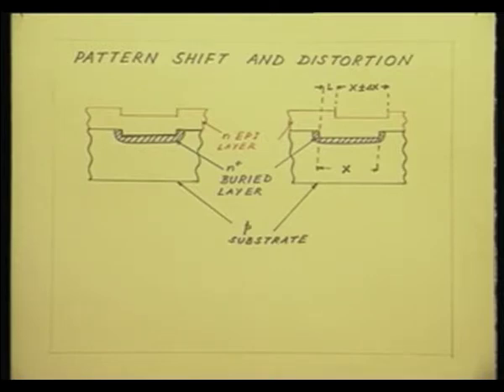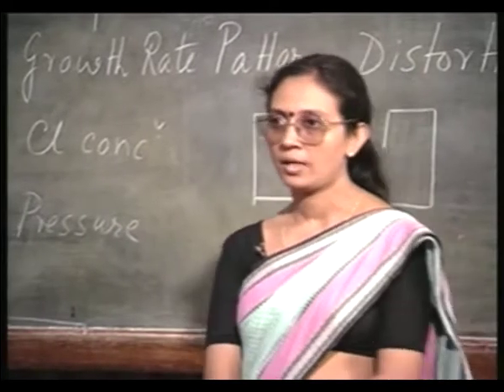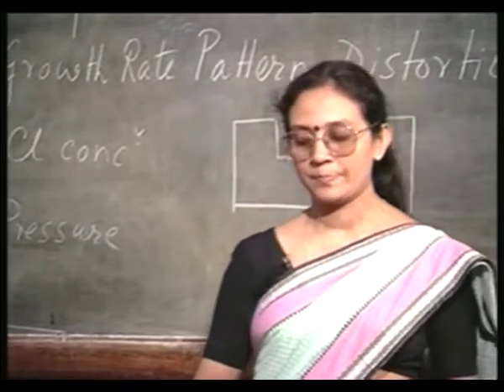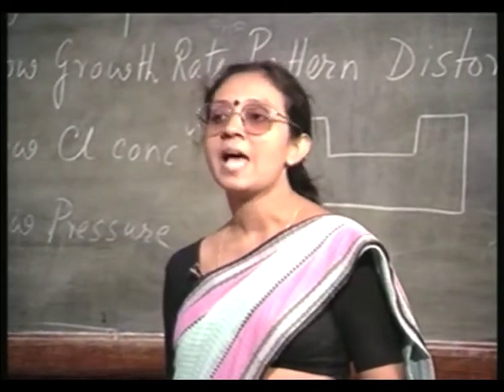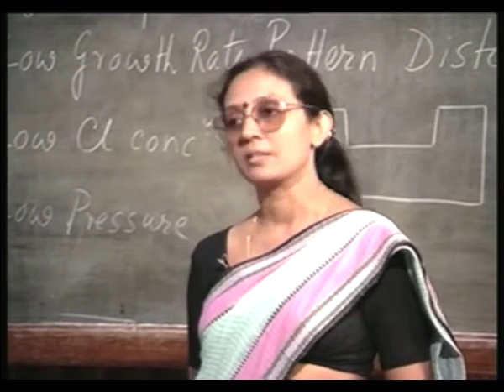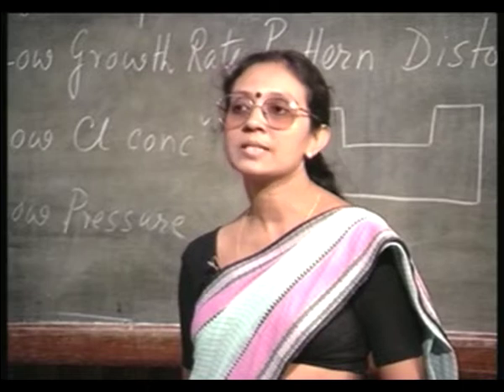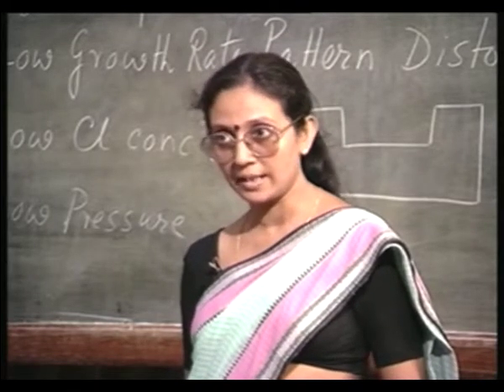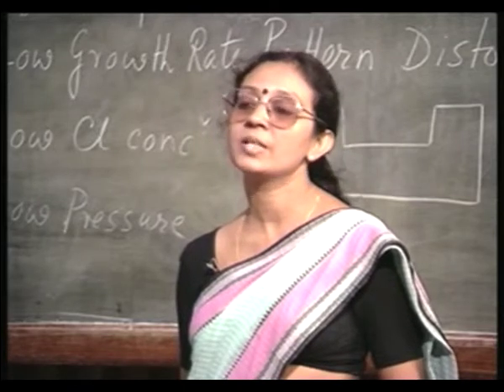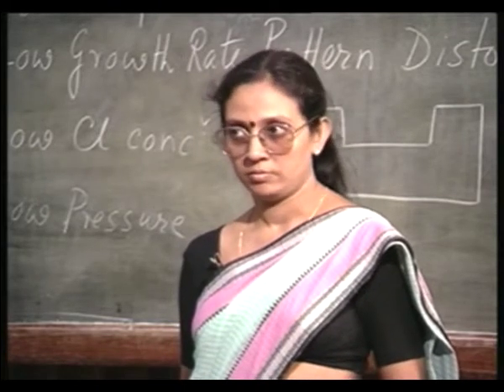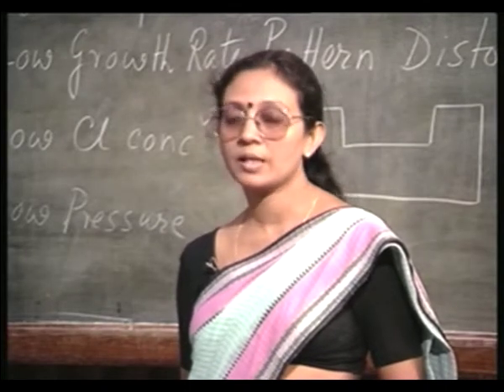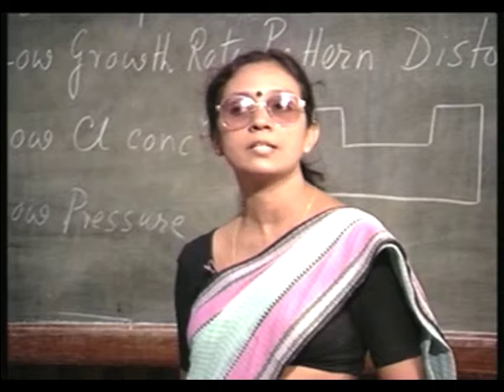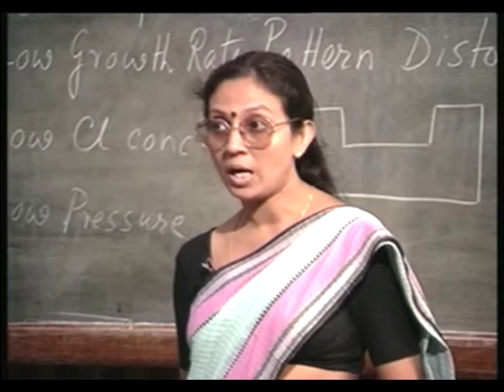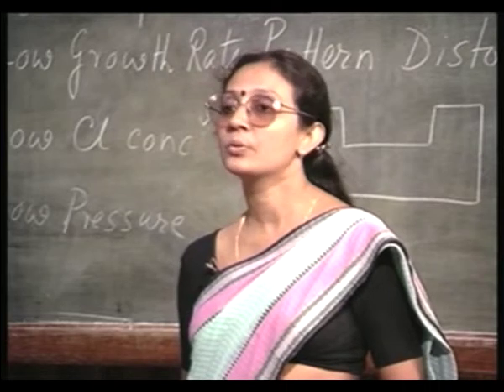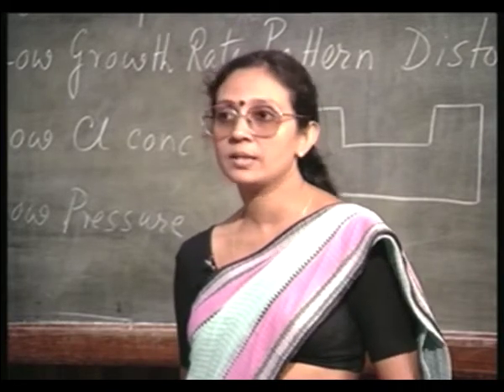Now that we have grown an epitaxial layer, the next point is how good is its crystal quality. Let me tell you something. The epitaxial layer is only as good as the bulk crystal is, because you are growing something on top of an already existing layer, and as I said, the term epitaxy itself means arranged upon. The crystalline quality of the epitaxial layer comes about because of the underlying crystalline symmetry of the bulk layer. So, unless the bulk layer shows a very good crystalline symmetry, you cannot expect anything to be arranged upon that.